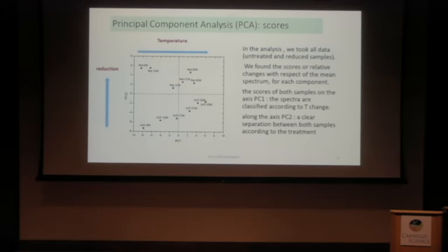And you can see that the reduction has more effect if you are at low temperature. So we have a clear separation between the effect of temperature and the effect of the reduction by this analysis.